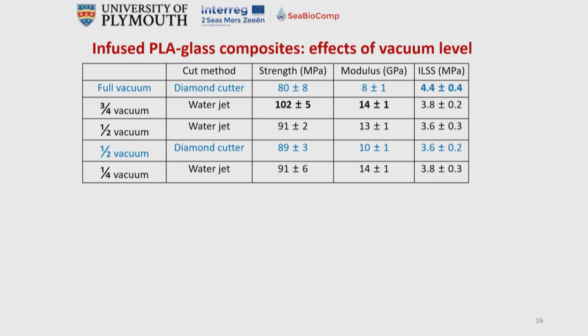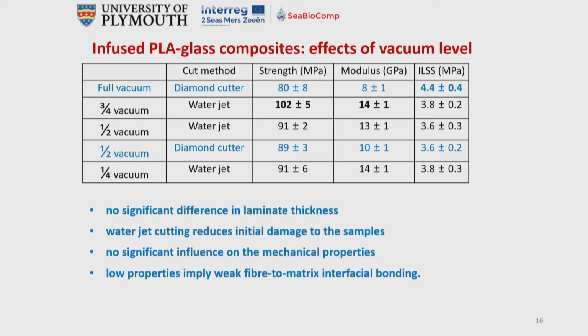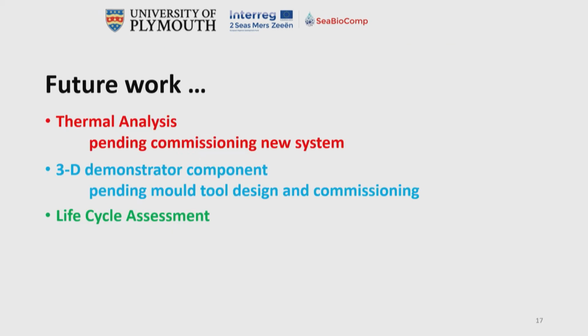We tend to pull the best vacuum we sensibly can when we're doing thermoset resins, and that may not be the best option for our PLA composites. In this particular set of tests, there were no significant differences in the laminate thickness, dictated by the pre-infusion pressures. There were some issues here, it's a long story, and it wasn't possible to complete the full series of tests. Again, low properties, implying weak interfaces.